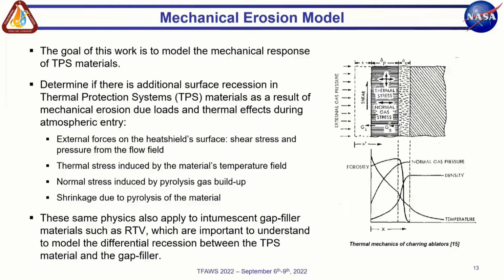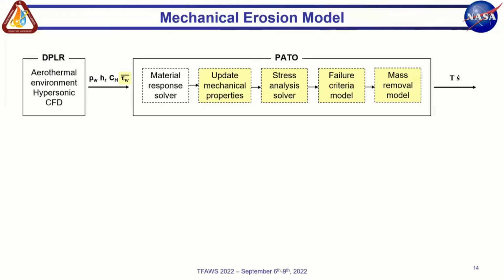So the same physics also apply to intumescent gap filler materials such as RTV, which are important to understand to model the differential recession between TPS material and the gap filler. And this part of the presentation is an overview of the mechanical erosion model implemented in PATO that accounts for this potential additional mass removal, specifically during high shear conditions. This slide is a flow diagram that shows how the mechanical erosion model was implemented.